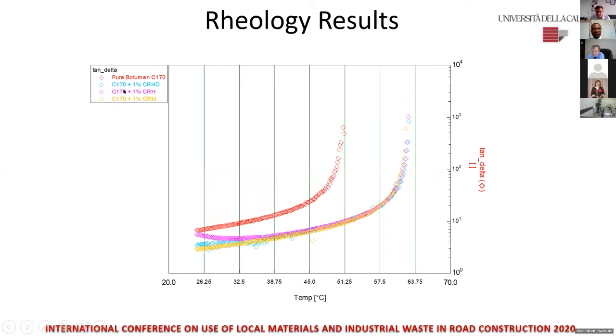Now, this is another rheological result, of another bitumen sample, which is the soft bitumen, the one with a penetration grade of 170 to 210. You can see that because of the nature of that bitumen, because it is softer, the pure bitumen has a transition point around 51 degrees centigrade, which of course means that the bitumen is softer.